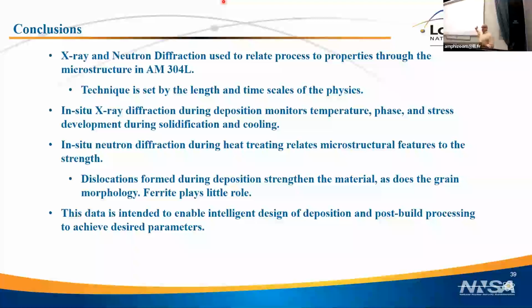We collected in-situ data, just like the steel that I showed you, depositing titanium. The reason I don't ever show that data to anybody is because I can't figure out how to interpret it. I have great data of the titanium, in fact, my student did publish it. I wasn't a big fan of him publishing it. We can show the lattice parameter, the 110 peak and the 002 peak, changing with time, but I can't separate where the vanadium is from the temperature. They're very similar size effects.